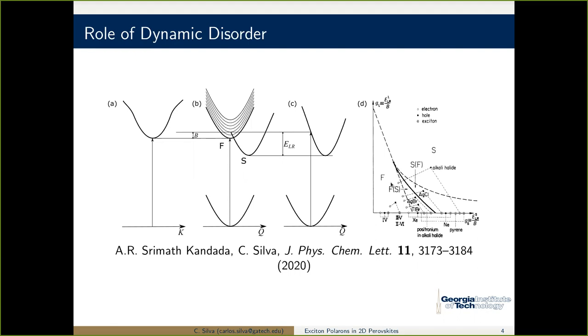That allows us to then draw a phase diagram of whether the excitations, the electron, the hole, or the exciton, are free excitations, self-trapped excitations, or somewhere in between, where they might have some degree of delocalization but are not free excitations. They're still dressed by the lattice. If we look at classical semiconductors, we're down here, where the long range couplings are going to dominate. If we look at the organics, pyrene is the example here, there are very short range electron-vibrational couplings, couplings of charges to very local carbon-carbon stretches, aromatic carbon-carbon stretches, for example. That is in this site where excitations are self-trapped, or we can think about Frenkel exciton regimes, for example.